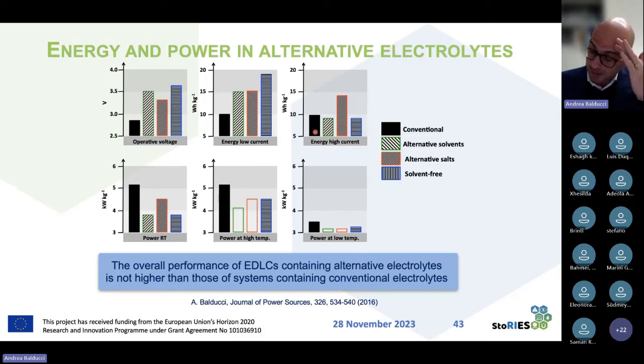Because typically these solvents or electrolytes are more viscous than the one based on acetonitrile. And this viscosity is basically limiting the mobility of the ions. So when we apply our current and we are asking our ions to move very fast, they are not able to follow this. And this is then well seen also in terms of power, because when we are replacing the electrolyte with an alternative, typically we can increase the energy a bit, but we lose in power.